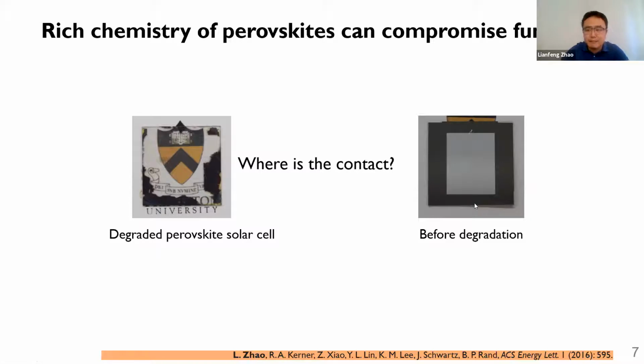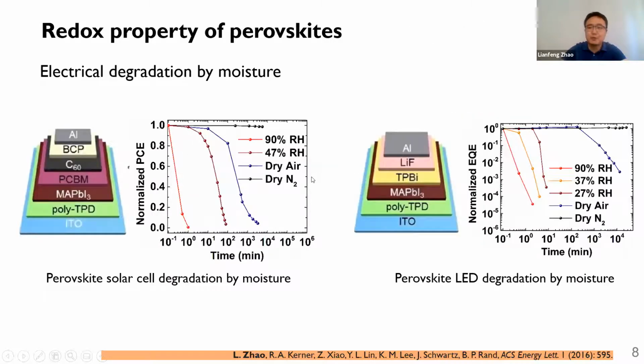Of course, this is an extreme case, but it shows the importance of a deep understanding of the chemistry in the device. The reactions between perovskite and the electrodes have made the full device stack fully transparent after device degradation. And I will show you more details about these reactions. It is well known that both perovskite solar cells and LEDs are sensitive to moisture. But at that time, it was not clear what the mechanism was. People have proposed that it is the water molecules that decompose the perovskite thin film that induced this device degradation. But what I found is that the degradation is induced by the chemical reactions between the electrode and the perovskite.